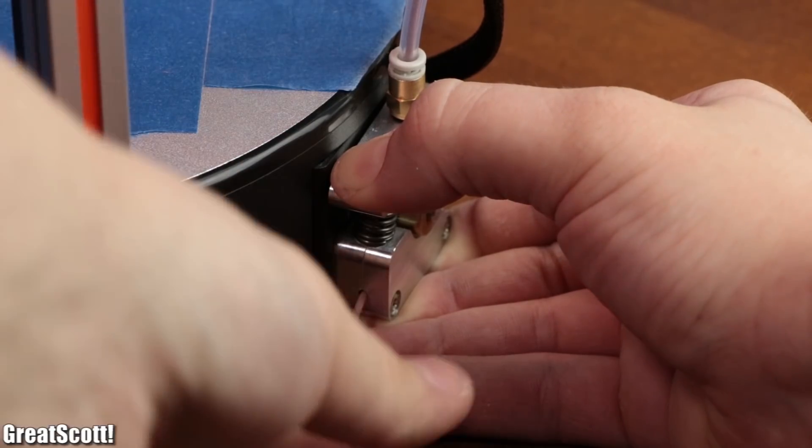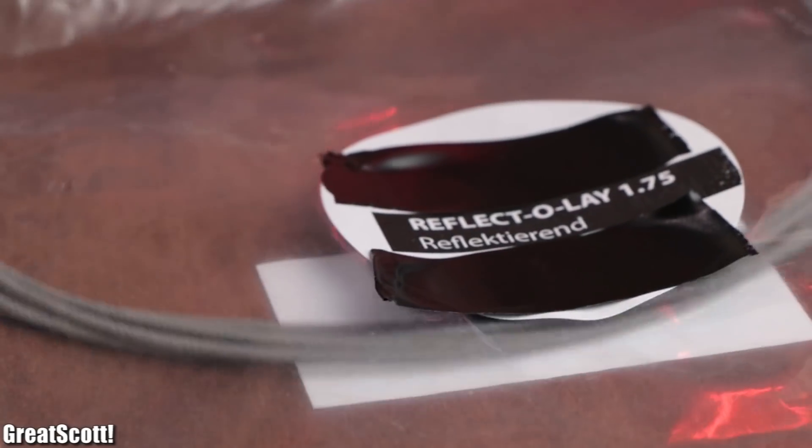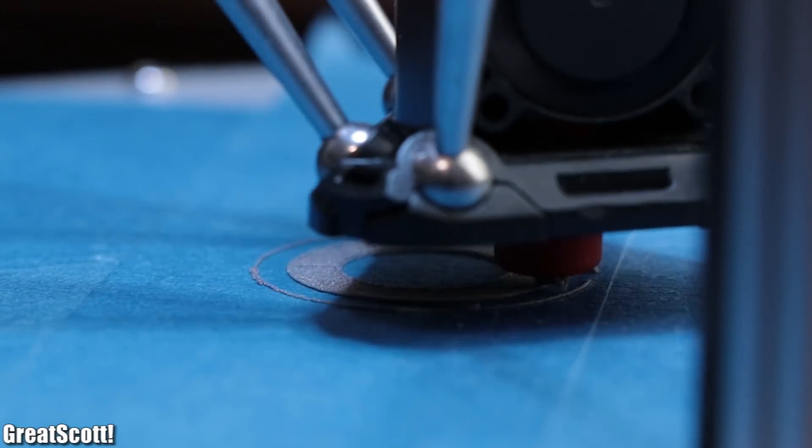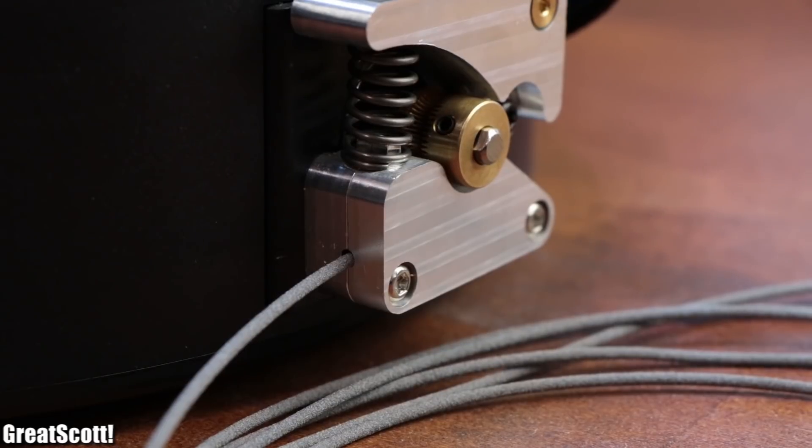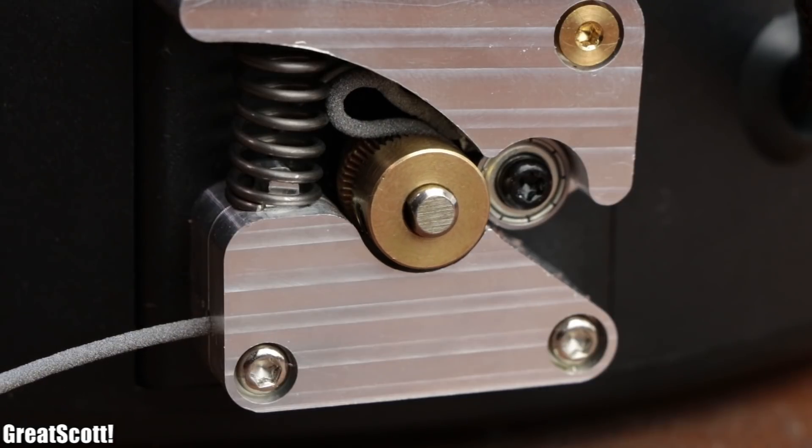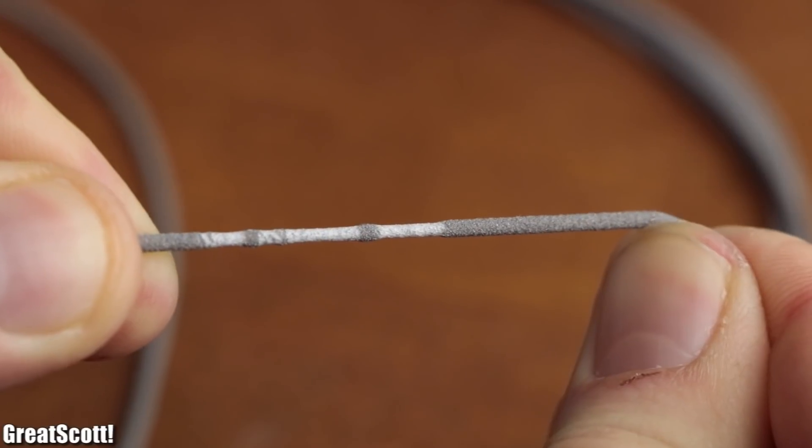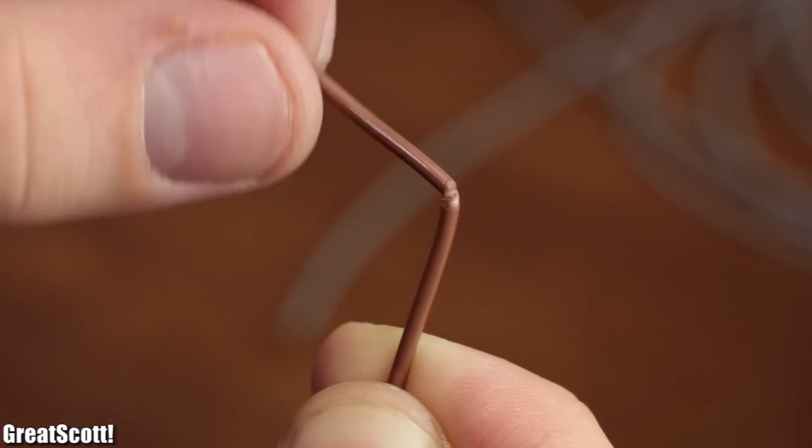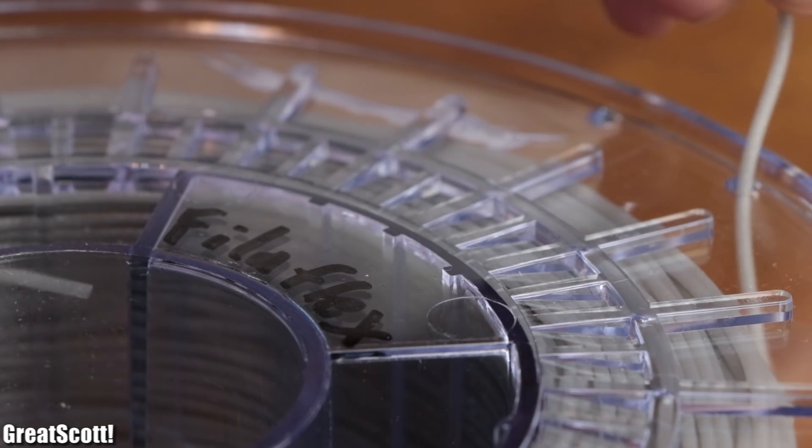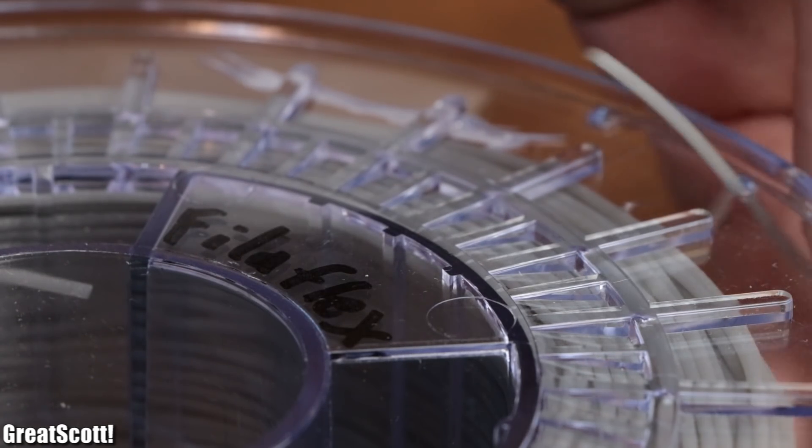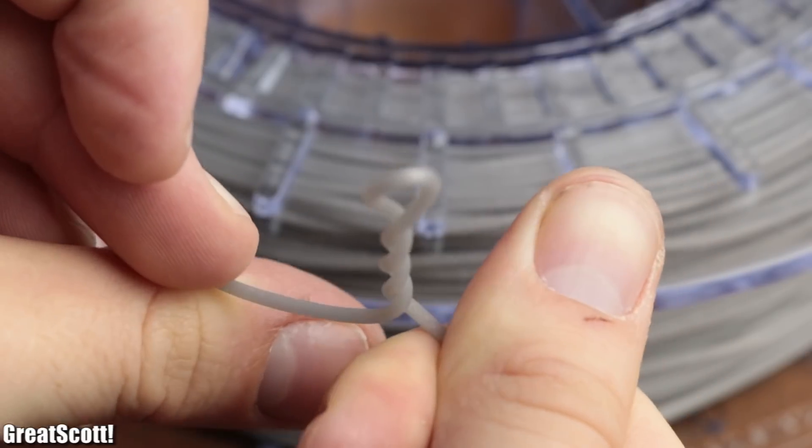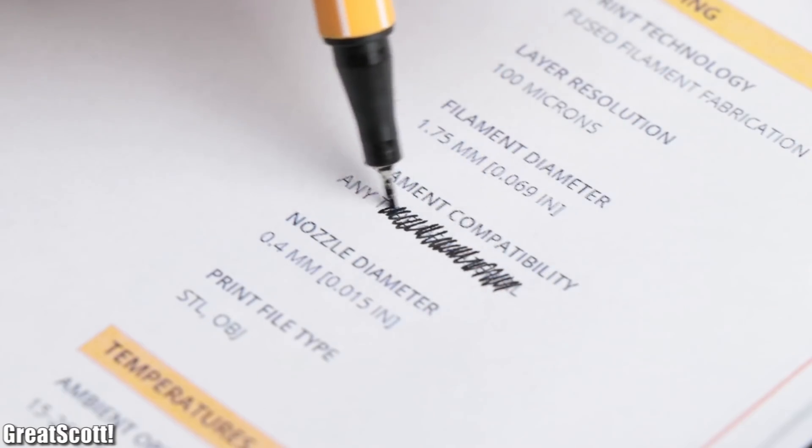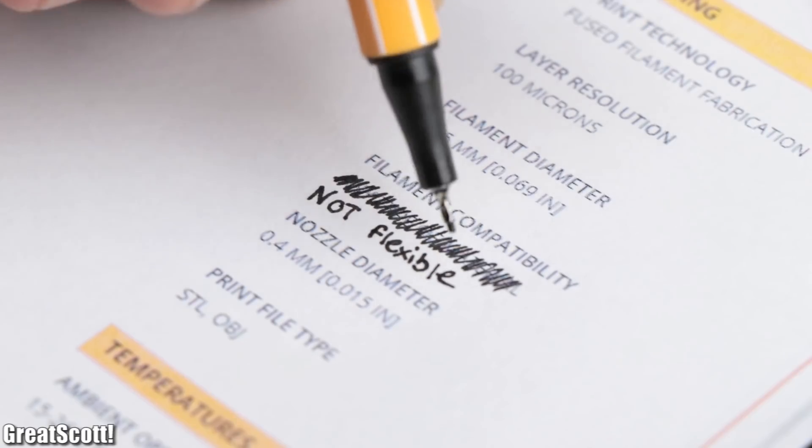Now since I was on a run at this point, I tried some flexible filament, which started out just fine. But eventually the extruder could not push it with sufficient force and clogged itself. The reason is simple: this filament is a lot more flexible than the other filaments I tried so far, which sadly also means that any kind of flexible filament cannot easily be printed with the Delta Go. So let's fix their website real quick and move on to the last material test.